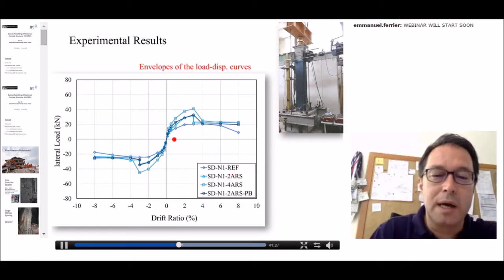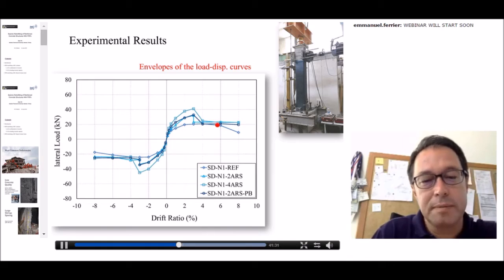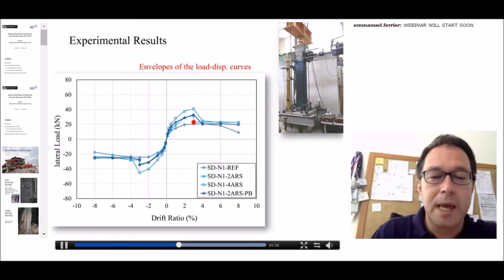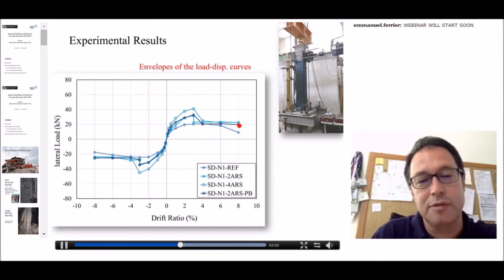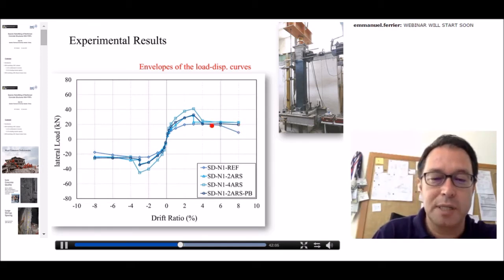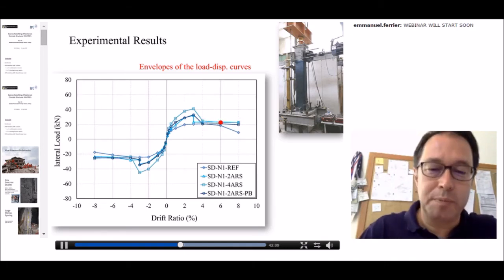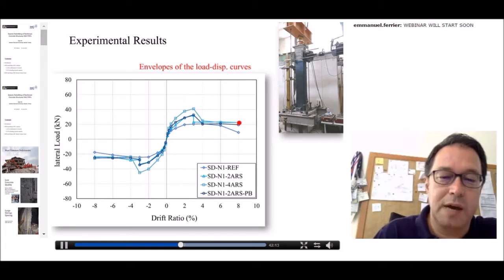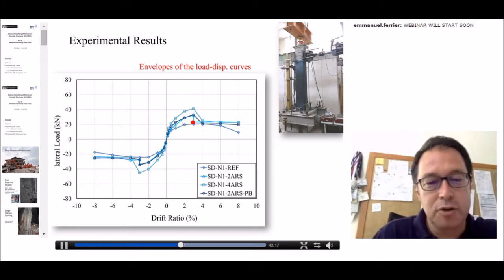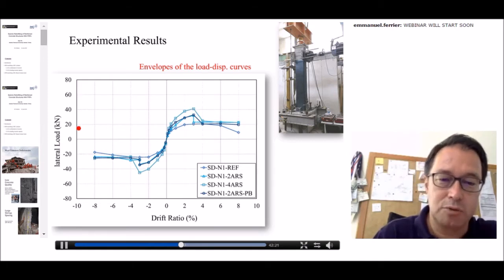But anyhow, if you look at the performance of the reference specimen and compare the retrofitted ones, as you see, up to 3% drift ratio, performance is much better in the retrofitted ones. But upon reaching 3% drift, we have the fracture of longitudinal rods or laminates, and then strength is lost. So we have almost the same strength at around these drifts. Then with increasing drifts, because we don't have confinement in the reference specimen, of course we lose the strength. Up to this point, because of the contribution of transverse CFRP, we have a ductile behavior. So basically I could say that because of the longitudinal FRP bars, we have a strength increase like that, which is quite significant, up to double.